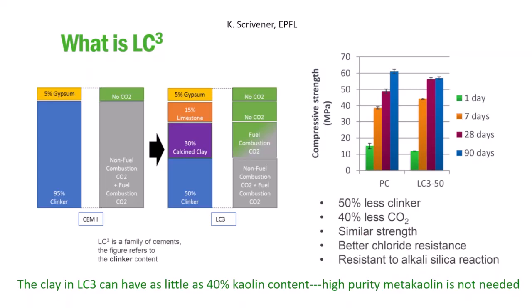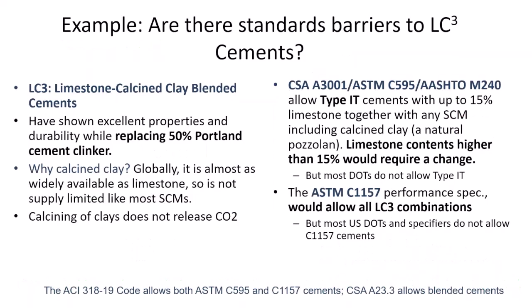A calcined clay is already allowed. It's already been used in concrete in North America, but typically the high purity metakaolins. Now there are companies making these lower grade. I think Ash Grove has a plant now in Nebraska, and I understand that Holcim is doing that in Utah now, calcining clays. And then they can blend that with the limestone cement and make a Type IT cement that is allowed now under the standards in 595. And you can get similar strength performance, better resistance to ingress, and resistance to other types of degradation mechanisms. And you don't need the high purity material. You can use the stuff that the China clay people and the pharmaceutical industry clays throw away as waste, as the raw material.